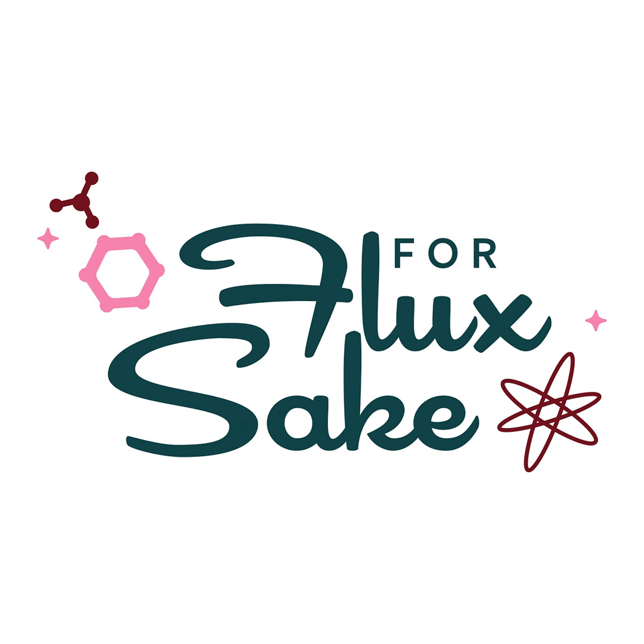The glazes that look like they do something interesting come down to what is going on in those glazes. The number one thing that people find interesting in layering glazes is putting a matte glaze on top of a glossy glaze. Why? Because a matte glaze has crystals that grow inside of it. So as that glaze on top submerges into the glaze below, the glass will begin to homogenize into the underglaze, but the crystals will not dissolve as easily because they have formed as this independent chemical thing. So you'll get these little spots of crystallization throughout that glaze. So that can be interesting.